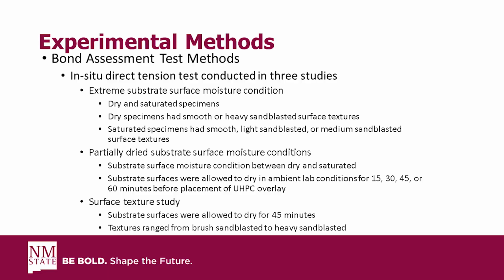So we did a partially dried substrate surface moisture condition, and this is where we implemented the timing, and this is where we did the 15, 30, 45, and 60 minutes, with that 45-minute being that last case where there's visible moisture on the surface.